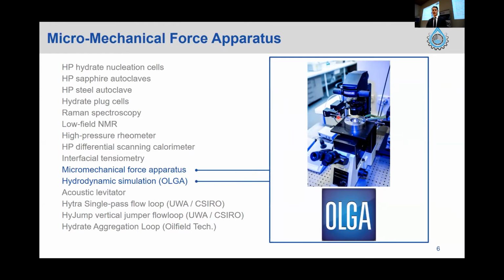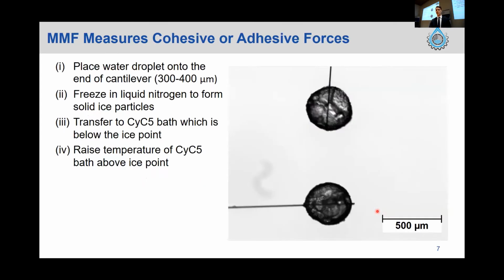And basically on either side here, we have a cantilever that's held by a micro manipulator. So the cantilever on the left holds the hydrate particle that's formed, and the cantilever on the right holds the substrate, in this case, the thermoplastic composite substrate. And then a little bit of the research performed at the end was using the OLGA simulation to sort of validate a potential technique. So just to talk a little bit quickly about the MMF procedure.